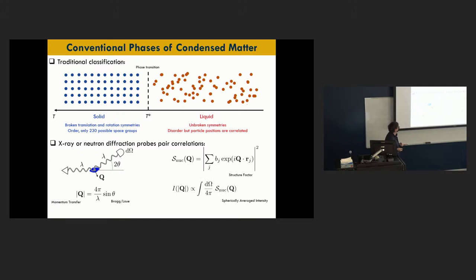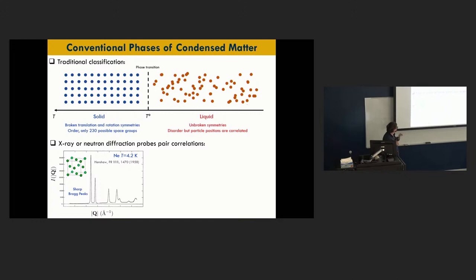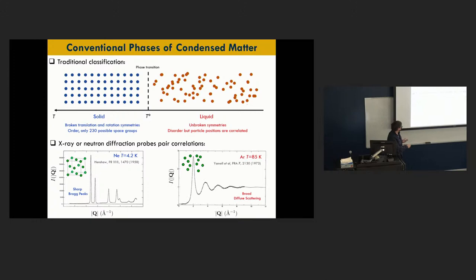So one example here, very simple, is just a solid neon, and you see here a Bragg diffraction of solid neon. This is an old PRL paper from the 50s, and you see sharp Bragg peaks that are characteristic of the solid. Okay, but of course you could warm up that system. Here it's argon, and neon is essentially the same.